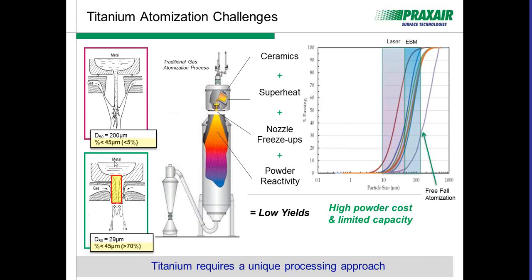What Praxair developed and operates is really a proprietary nozzle. So this proprietary nozzle is designed to superheat the liquid titanium very rapidly. In a fraction of a second, it can add superheat coming out of this water-cooled copper crucible that allows the liquid to be atomized using this close coupled technology.